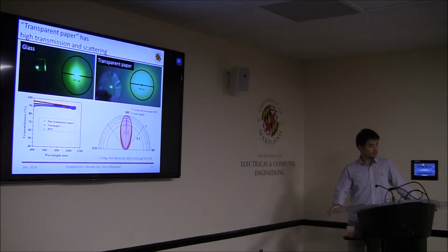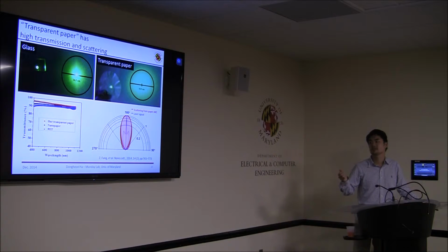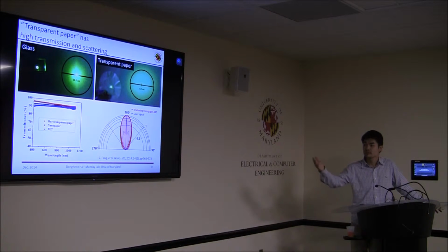So from experiment, we have shown that this paper really has large scattering and high transmission. The left picture shows what happens when a green laser shines on a glass slide, and compared to the left picture, the right picture shows the same thing on our transparent paper, where it scatters light very well. And from experiment, we have shown that this paper has really high transmittance. It is even greater than 90% sometimes.